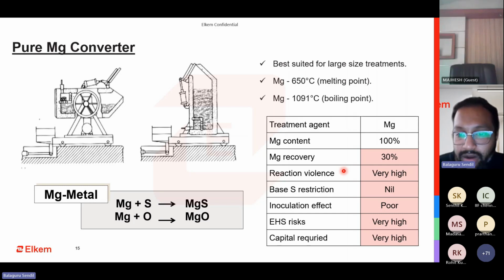The other one, the capital required is also quite high. But one advantage here is that the base sulfur restriction is not there. This is especially used by people who have converted from cupola, but still some of them who are using cupola. This is a very useful tool for them. If base sulfur is more than 0.03 and they want to do duplexing in an induction furnace, if they don't want that, then pure magnesium is a good option. Again, the treatment size has to be on the higher side. If it is for 500 kg, 600 kg or a 1-ton treatment, it will be very difficult to justify the cost of using this particular process.